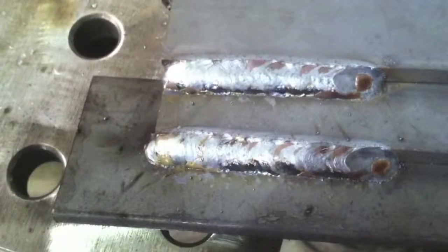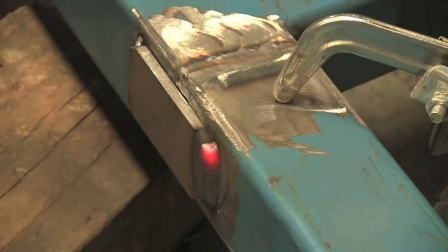Typically, at higher currents, it's not quite as smooth an arc, and it gets a little bit of spatter, and you can see right there I got a little undercut. But at lower currents with smaller diameter wires, even though there is a much tighter sweet spot that you have to adjust and tweak your settings to find, you can get a really, really smooth, nice arc.